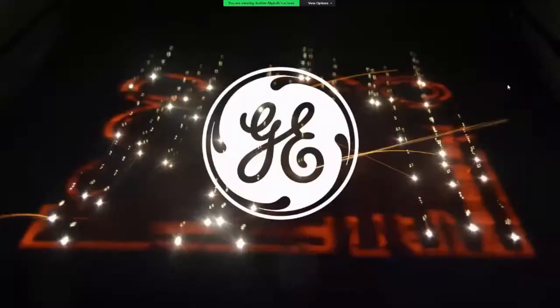This is in production today for turbine blades in the GE Aviation family, with an expected production rate of more than 60,000 blades per year for the GE Aviation 9X engine. Due to the 50% lower density of titanium aluminide compared to conventional nickel-based superalloys, the weight of the engine is dramatically reduced, making it more fuel-efficient — which is critically important for the aerospace engine industry.